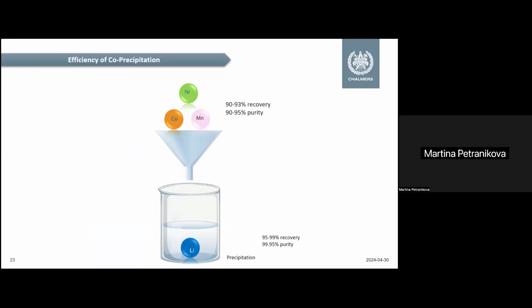Because for some companies, this can be either too difficult or too expensive a method to be used, what is also applied these days is just co-precipitation of the transition metals. And then again, lithium stays in the solution and can be used, but the purity is slightly lower for the transition metals product.